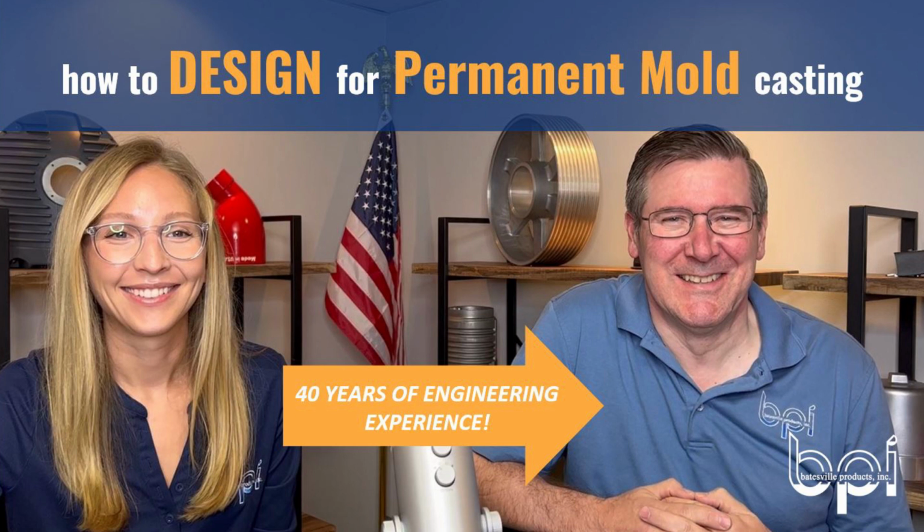And the way these castings fill in our tilt pour permanent mold casting process, you can be assured that the metal will fill around whatever insert you're using, and that it'll gently squeeze that insert so it isn't a metallic bond, but it's tightly held in place. So it becomes a functional part of whatever you're trying to create. I'm really excited whenever we get the chance to do some functional inserts.